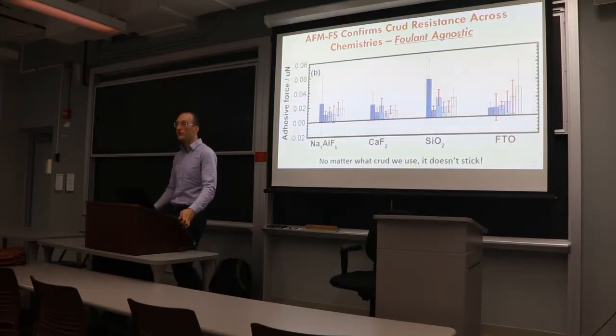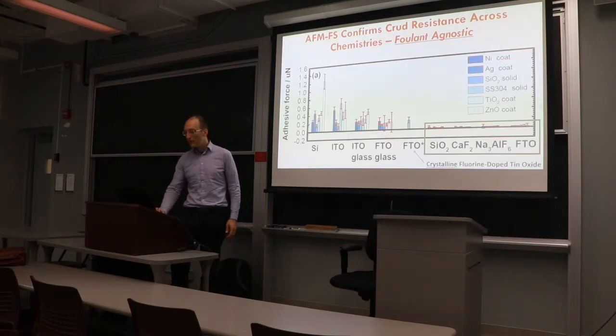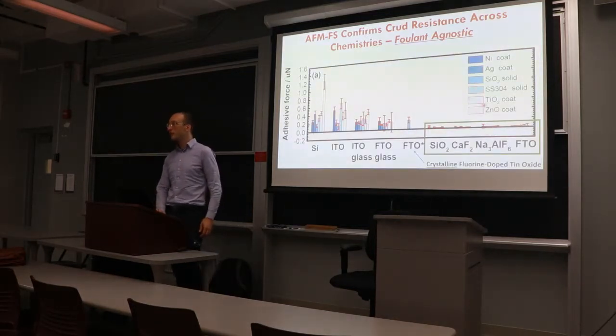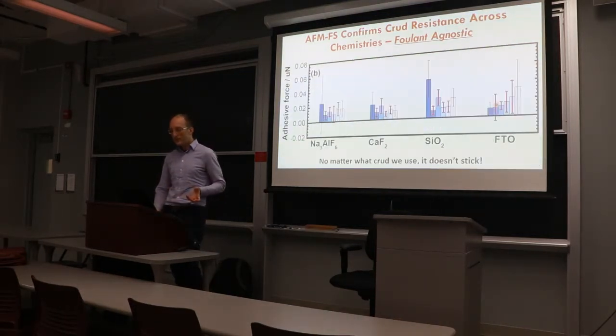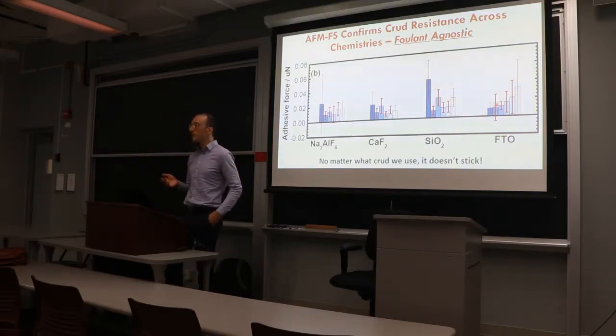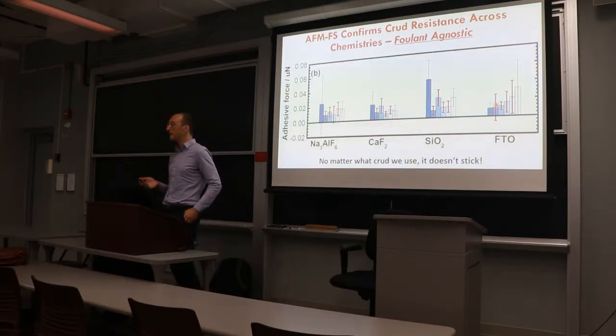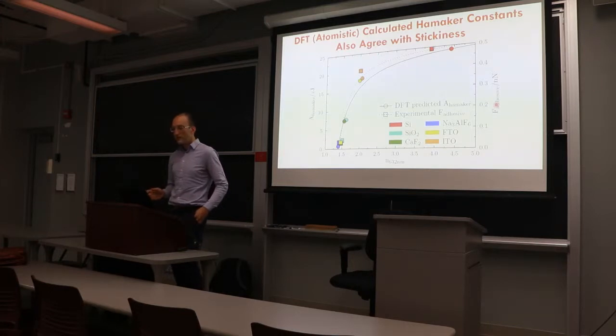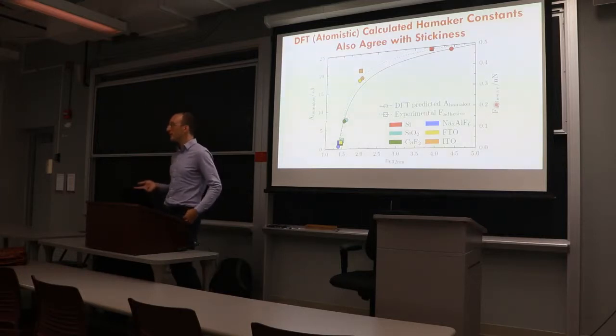But one important thing to note here is that no matter what foulant we threw at these slick coatings, the stickiness was statistically the same. So these are what's called foulant agnostic. And the theory predicts this as well, but now we've been able to experimentally verify it. And then last thing for the simulationists in the audience, we've also done DFT, or atomistic density functional theory calculations of the slickness of these surfaces, and everything agrees pretty well. So the theory and the lab scale experiments and the reactor scale experiments all seem to be matching.